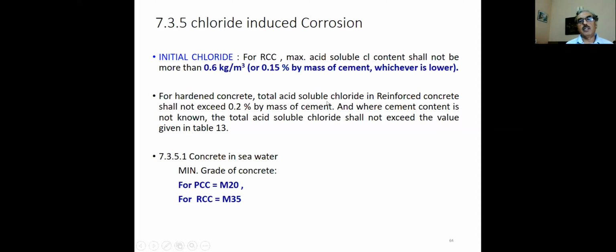And for hardened concrete, how to determine this we have mentioned separately. Total acid soluble chloride should not exceed 0.2% by mass of cement. And where the cement content is not known, there also the values have been given.